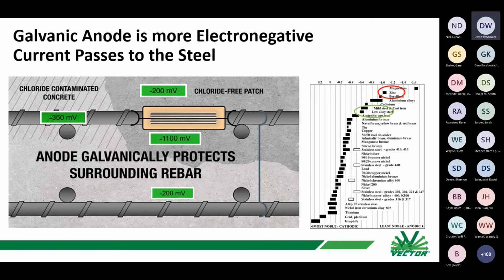If you look at the galvanic series shown on the right-hand side, you've got steel here, and you've got zinc over here. You've got generally between half a volt and 1 volt difference in voltage between zinc and steel. Coupling this zinc anode to the steel puts something into this localized environment that is more negative. Once you couple these things together, current is going to flow from whatever is the most negative towards areas that are less negative. And yes, it will protect the steel that's inside the repair, which isn't really necessary because it's not going to corrode anyway, but it's going to be more negative than the steel in the immediately adjacent area. And so current is going to flow to those areas.